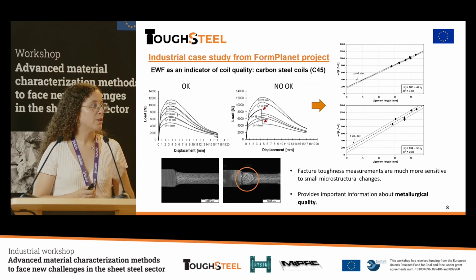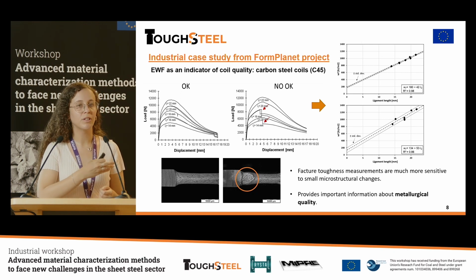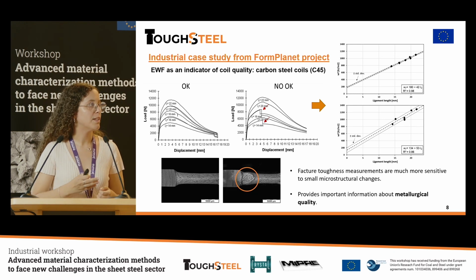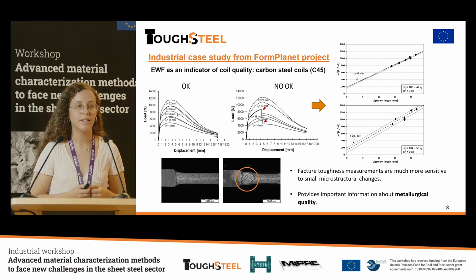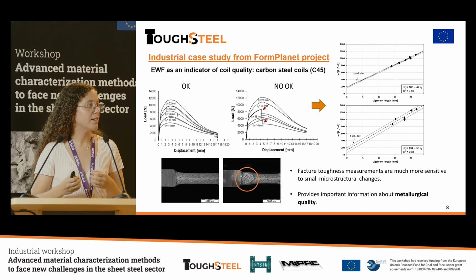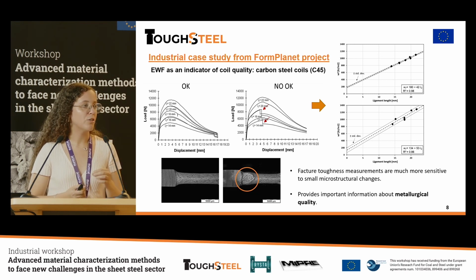What we could get from this case study was that when plotting the work of fracture values for both materials, one was presenting very good statistical values, and the other one was presenting more scatter in the result. This indicated that the quality of the material was not that good, and that the essential work of fracture method can detect these small defects in a material. So for coil quality, it would be a good option to study.